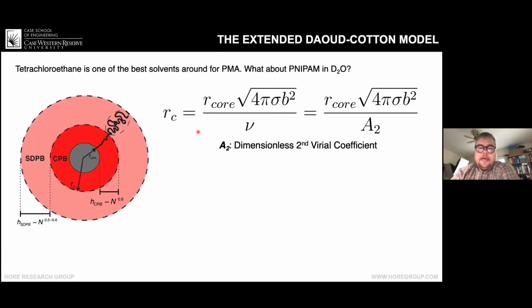So if we go back to the Daoud-Cotton model, the cutoff distance between these two regions, I filled in a little bit more of the details here, is a product of the diameter of the core, the grafting density, the Kuhn length, and the excluded volume. And this is exactly equal to the dimensionless second virial coefficient. So if we can get thermodynamic data, then we should be able to predict where this is, and we can test how well this model actually works for a responsive system.